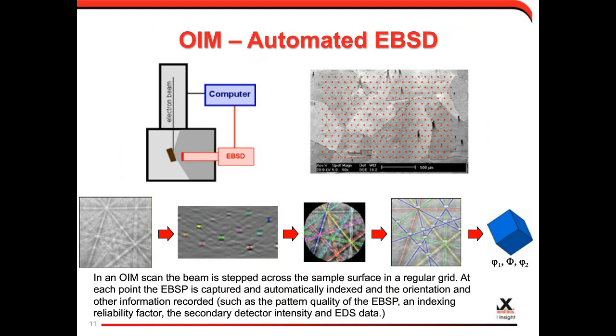So the way to think about OIM, or orientation imaging microscopy, is automated EBSD, or automated EBSD mapping. EBSD is an SEM-based characterization technique. You can see here on that little schematic in the top left, we take our sample, we tilt it to about 70 degrees, we fire the electron beam onto the sample, the electrons interact with the crystal lattice, they diffract within an individual grain, that diffraction comes back out, it's backscattered, and we detect that with our EBSD detector there. The reason we tilt the sample is so the electrons go towards the detector efficiently.